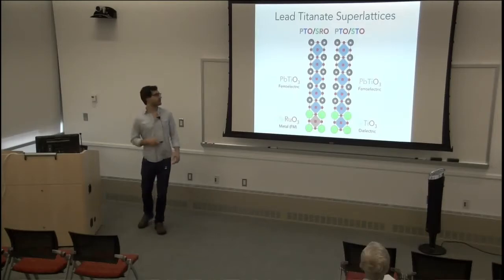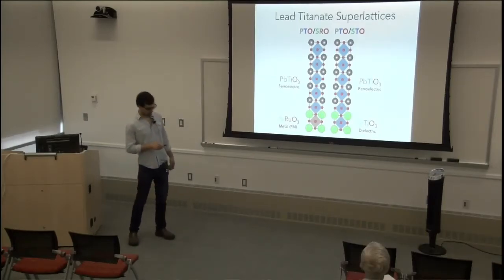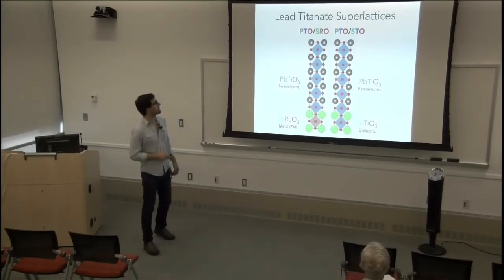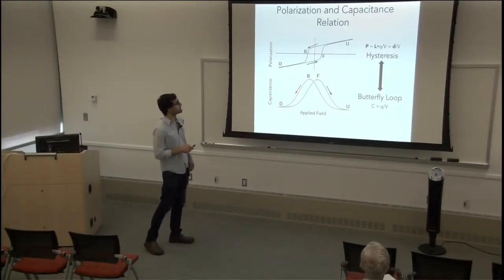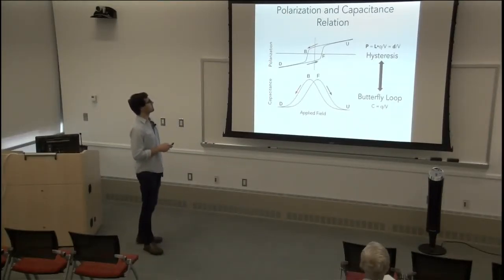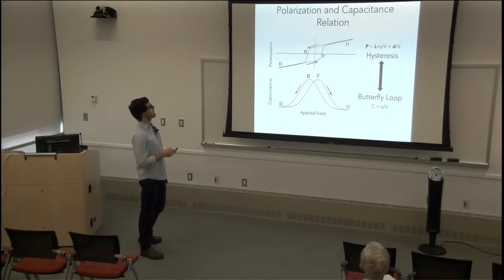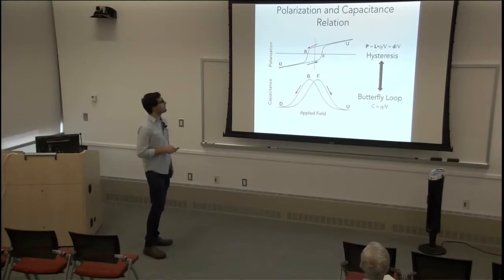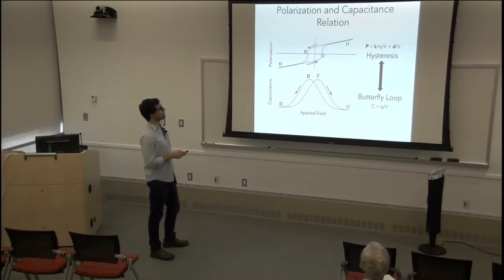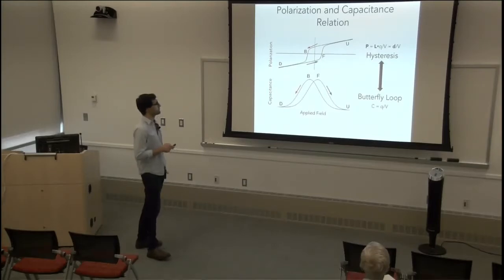Okay, so before I talk about experimental results of these things, I want to draw attention to the hysteresis again. Here on the top I have a hysteresis loop like I showed before. We're measuring this polarization, which is displacement times charge divided by the volume, or dipole moment divided by volume. And here I have the applied field.